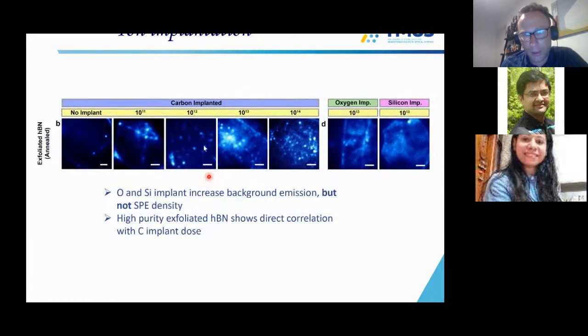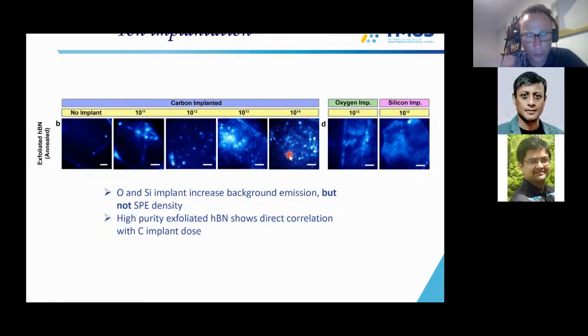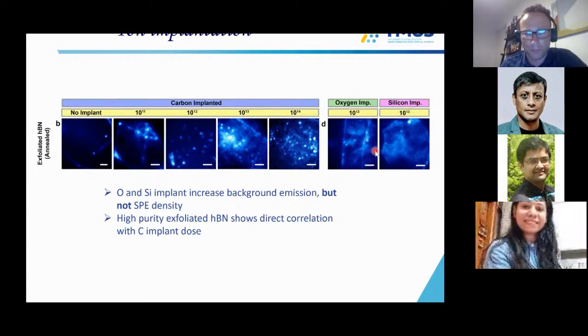So the last proof of principle is dose scalability. You can increase the dose from 10^11 to 10^14, and you can see the number of bright spots, which correspond to your single emitters, increasing dramatically. You can repeat the same experiment with oxygen and silicon and basically see no emission at all. So in this regard, if it walks and quacks like a duck, it's probably a duck.